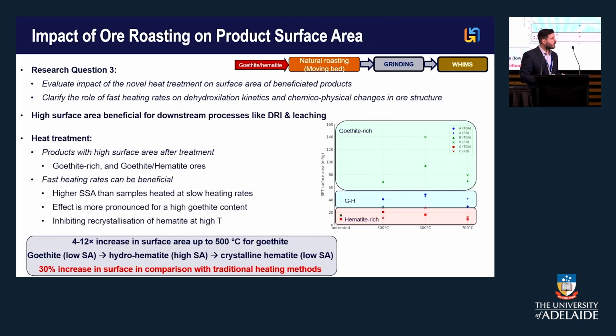The third question was about what's happening to the porosity. Porosity and surfaces is really critical, not so much for the beneficiation upstream, but rather for the downstream. So imagine if we have this green iron concentrate for a DRI, or for example, if we need a leaching for further recovery, porosity is critical. So we were able to prove that with the high flux methods, we can really upgrade the surface area. By how much? Depending on the goethite contents, but on average, you can get up to 10 times the surface area increase. This has a lot of impact on downstream process.